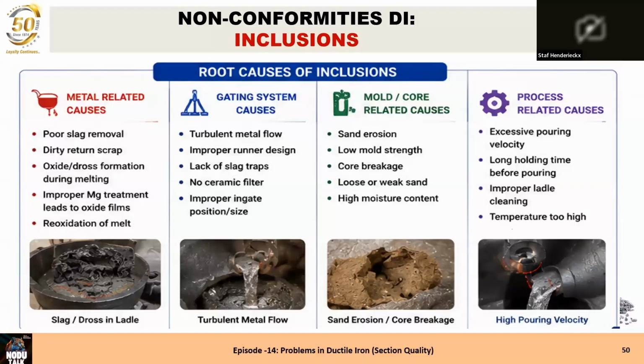And then an improper ingate and position of the casting can cause turbulent filling. Mold or core related sand erosion. That's not only the strength of the sand, but also the speed of the metal which is flowing over it. A low mold strength, of course, the lower the strength, the quicker the sand will go. Core breakage, especially cores which have different sections, and with an abrupt change from a thinner to a thicker section, there you have the possibility.